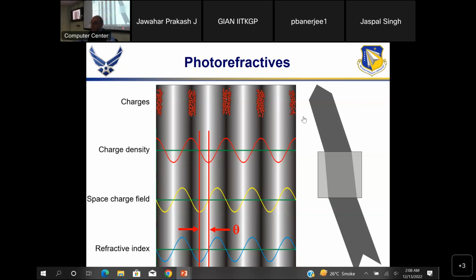But in the photorefractive crystal, that can be made up by the thickness. Because typically you can make them in the order of some millimeters, maybe 5 millimeters. So then you have enough change of the phase. These crystals typically you would use in the order of millimeters. Like the typical crystals would be this size, like 5 millimeters to 1 centimeter. That's the thickness, typically.